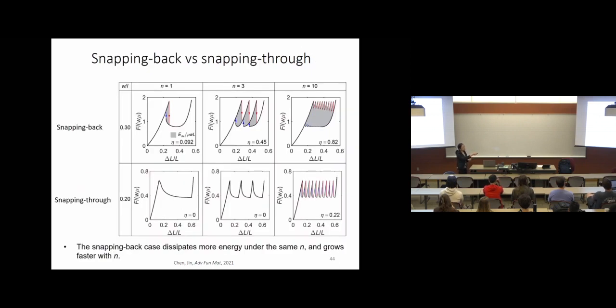Here I'm showing you the results for different numbers of layers and different width to length ratios, corresponding to the snap-back and snap-through cases. The shaded area corresponds to the amount of energy dissipation. What we can see here is that the snap-back case dissipates more energy under the same n and grows faster with n, so it's more desirable.